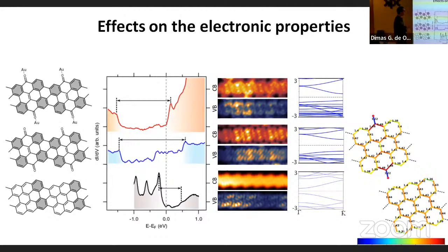When you go to the ketone functionalized ribbons, you see this dark blue bond here. So this is a very short bond, and this is the carbon-oxygen bond. This is the double bond, and this is a very short one. That's as expected. And then you see these very dark red bonds here. These are very long, because these are single bonds, right? So you see, we have much larger variations.